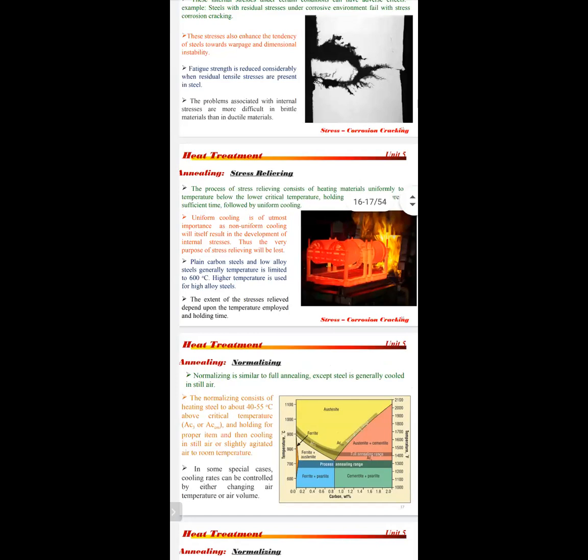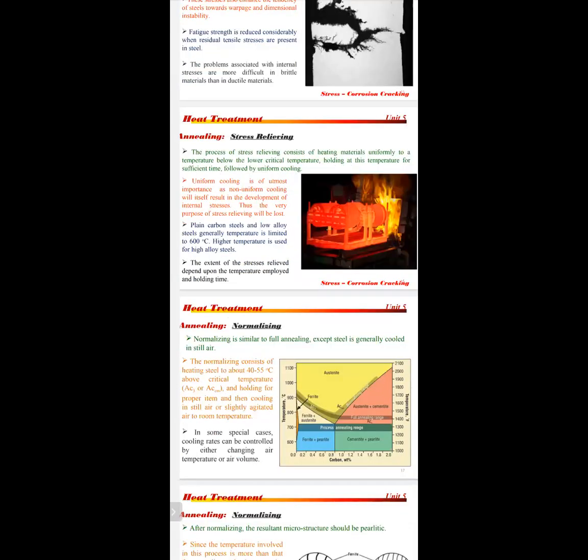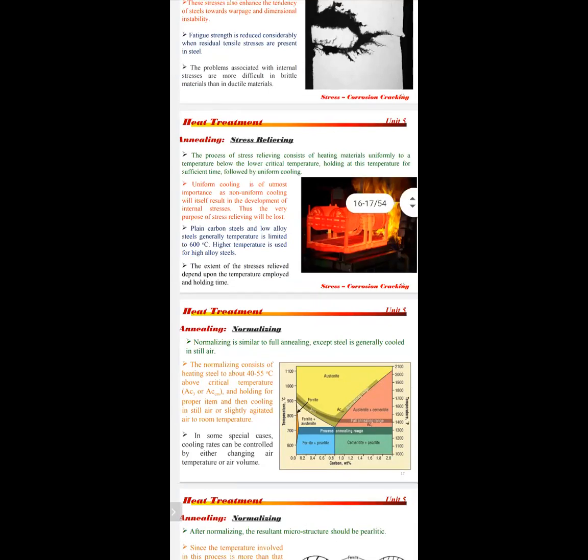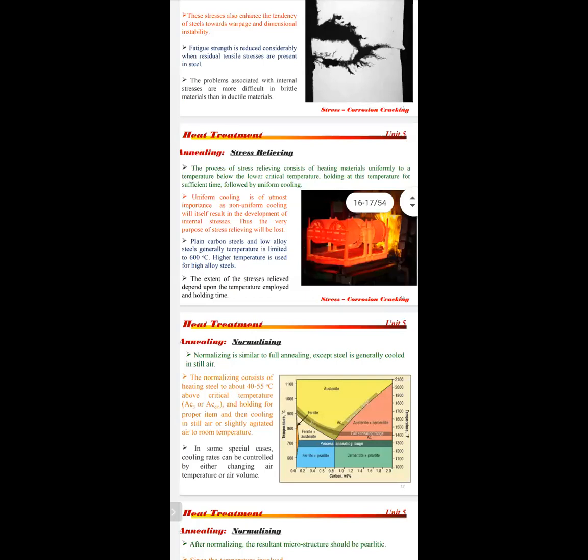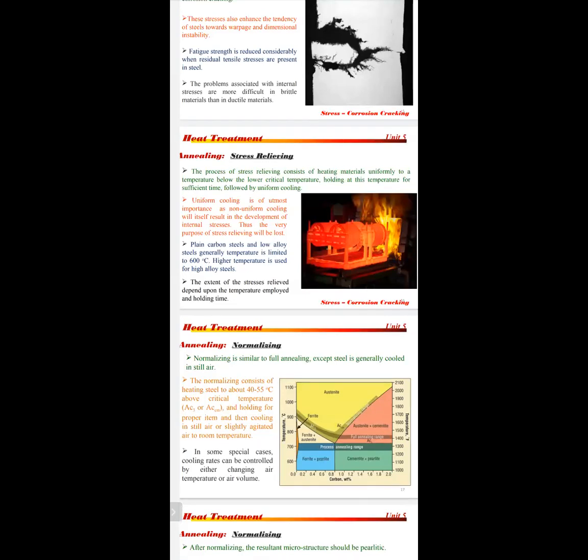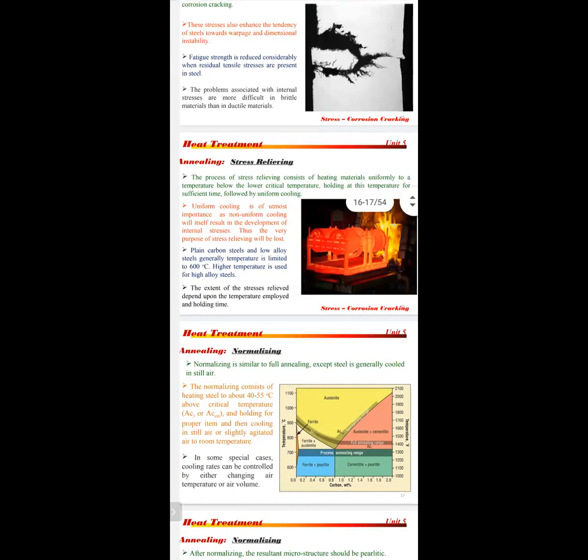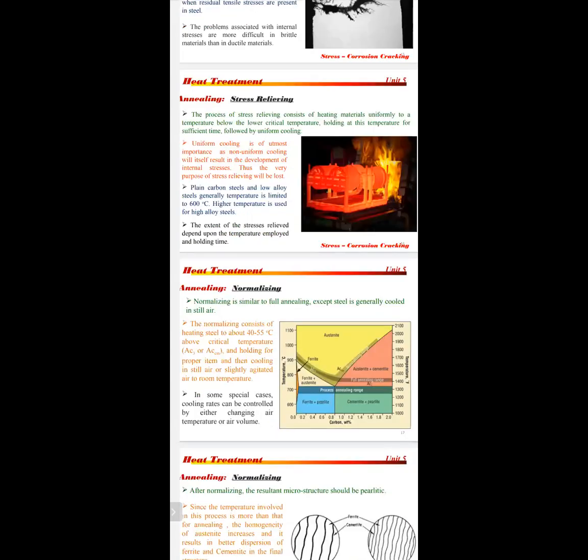Uniform cooling is of utmost importance, as non-uniform cooling will itself result in the development of internal stresses. Thus, the very purpose of stress relieving will be lost. That's why uniform cooling is very important. Otherwise, definitely there will be development of internal stresses. For plain carbon steels and low alloy steels, the temperature is generally limited to 600 degrees centigrade.